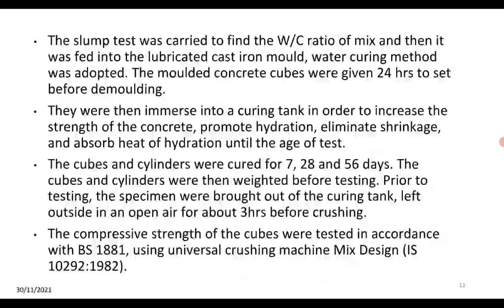A slump test was carried out to find the workability of the mix, which was then poured into lubricated cast iron moulds. Water curing was adopted. The moulded concrete cubes were given 24 hours to set before demoulding. They were then immersed in a curing tank to increase strength, promote hydration, eliminate shrinkage, and absorb heat of hydration. The cubes and cylinders were cured for 7, 28, and 56 days respectively. Before testing, specimens were removed from the curing tank and left in open air for about 3 hours. Compressive strength was tested in accordance with BS 1881 using a universal crushing machine.